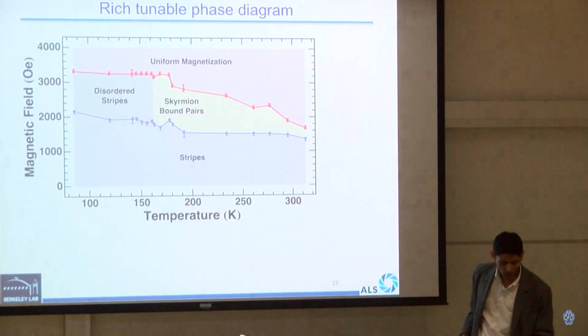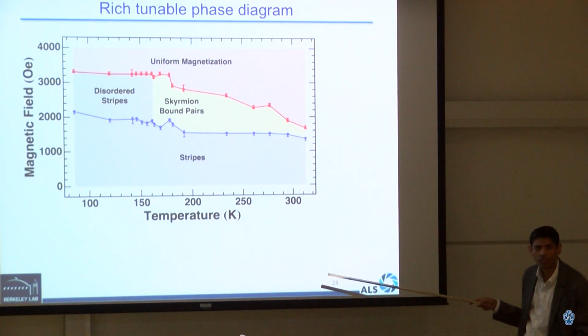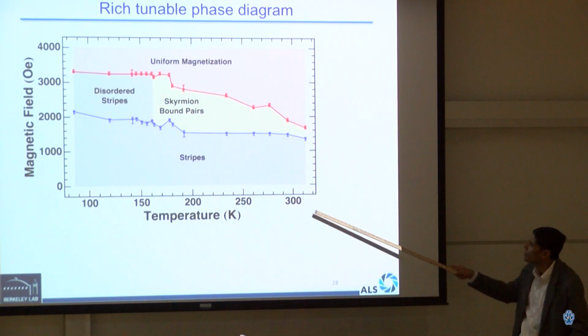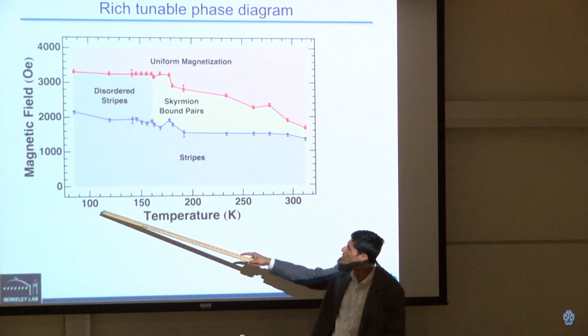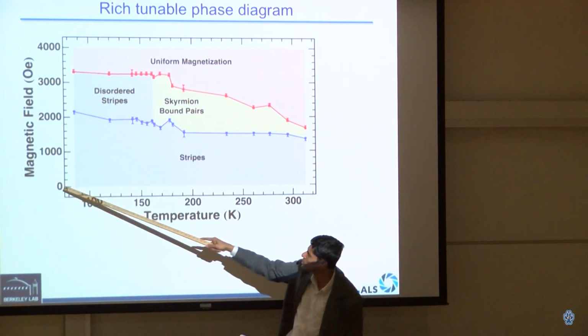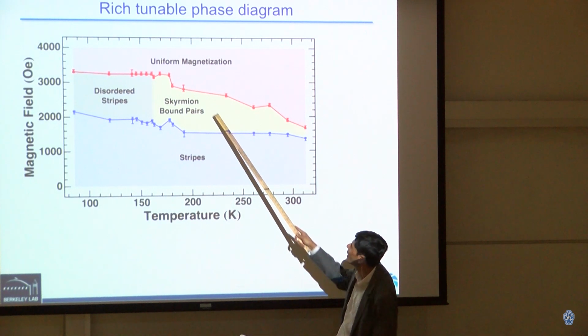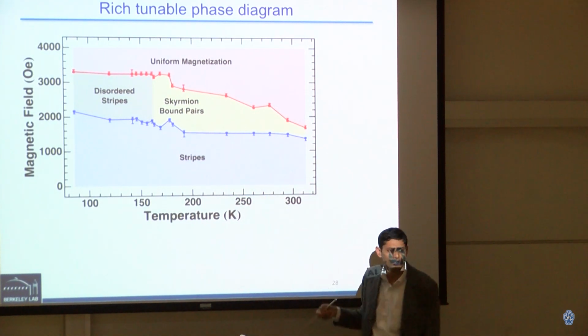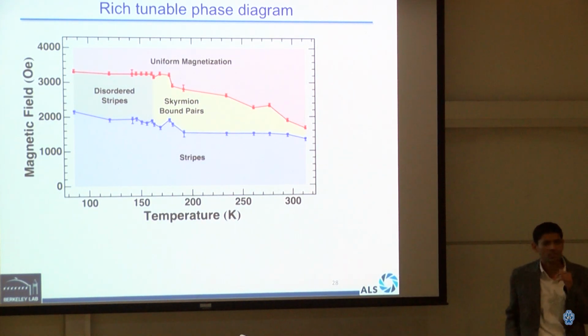And from there, I'm just not going fast here because I know that you have heard it before. What James did is that he figured out a very nice phase diagram of this material as a function of magnetic field and temperature, and you can see all these different types of interesting phases that appear in this iron gadolinium film.